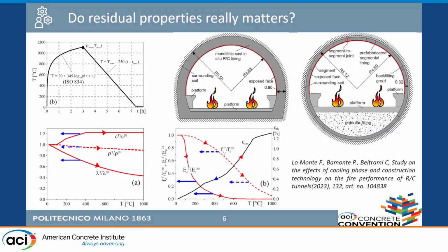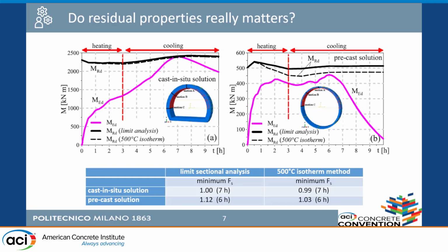And so we have to define also that during heating there is a decrease of, for example, here the compressive strength, but if I have cooling, I don't have a gain of the compressive strength, but I have to move horizontally because I leave the damage that I reached at that moment. So this slide was to show you a practical application in which residual conditions are very important, because in this tunnel we perform the structural analysis, taking into account also the cooling phase.